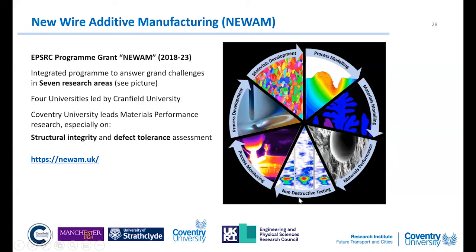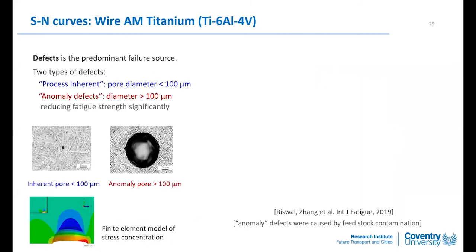And we are in collaboration with Strathclyde University on non-destructive testing with ultrasound technology. So the PhD student Romali did this work. So the defect is a predominant failure source. Actually, we tested 2 types of defects. One is a process inherent, so that is we can't avoid. And this is the gas porosity with diameter smaller than 100 micrometers.